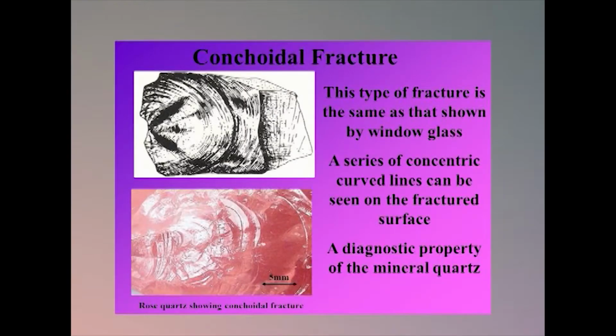We know that a fracture propagates perpendicular to the principal tensile stress, due to which the fractures tend to orient themselves in such a way that they continuously remain perpendicular to the principal tensile stress. So, when examining a radial fracture, the conchoidal lines meet the side which is opposite to the force at nearly right angles and then curve back asymptotically towards the side from which the force was applied, but in concentric fractures the tension is on the surface which is facing the force.